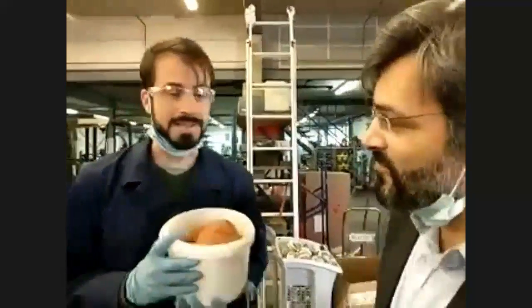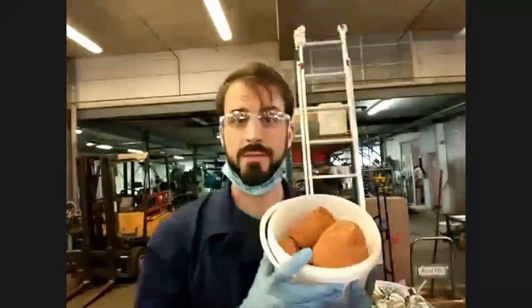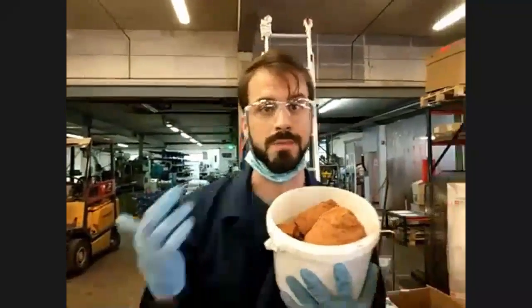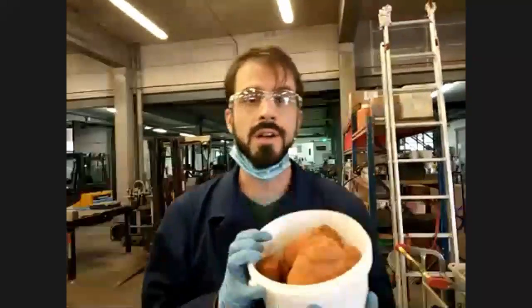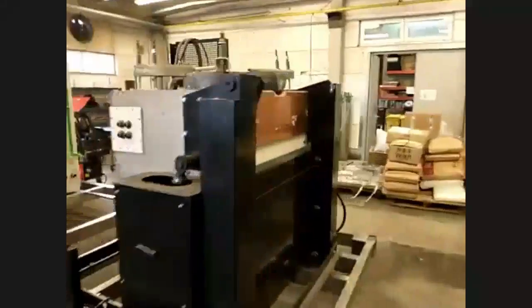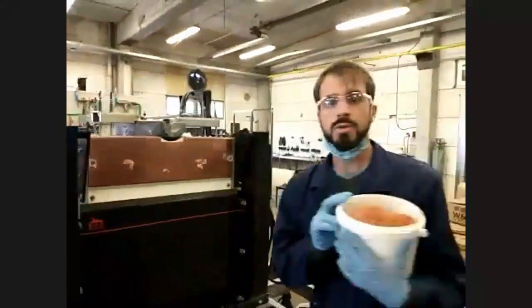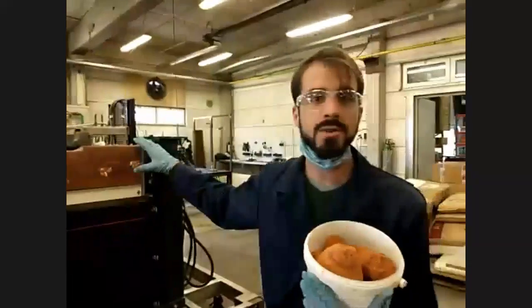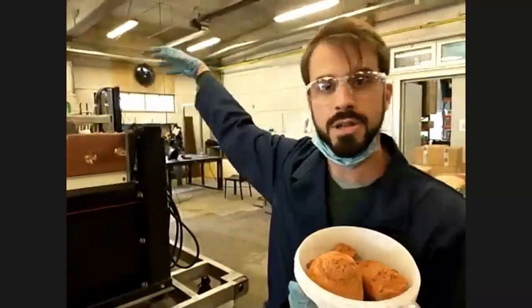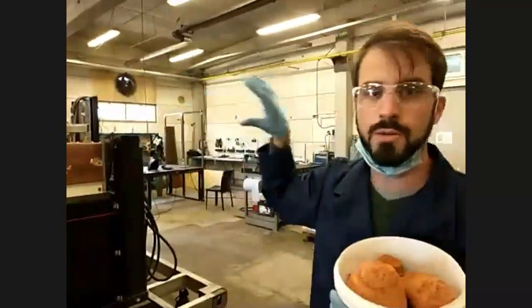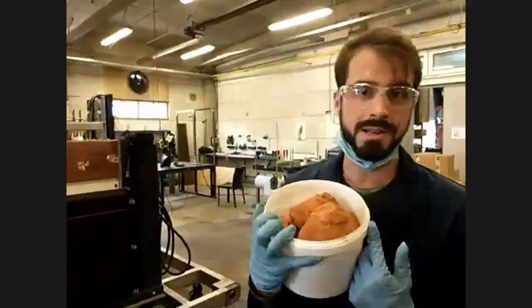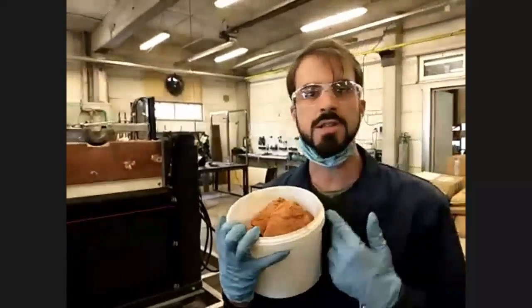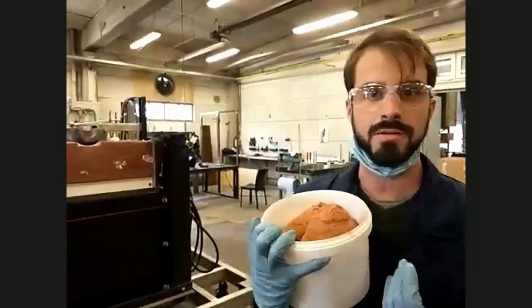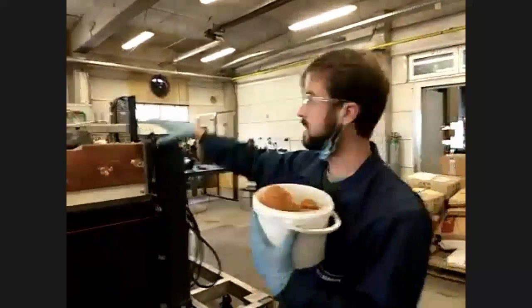Any idea? The best idea is that we go to our second container where you can transform this material into something different. So what you can see here is our heat treatment unit operation. And here is the furnace itself, which is an induction furnace. We have a generator in the back, which generates the heat for this furnace. What we want to do here is transform this material at high temperature, for instance, 1100 to 1300 degrees, into something which we can use to make a binder material out of it. So we put this material in the furnace, which we can maybe have a look at.